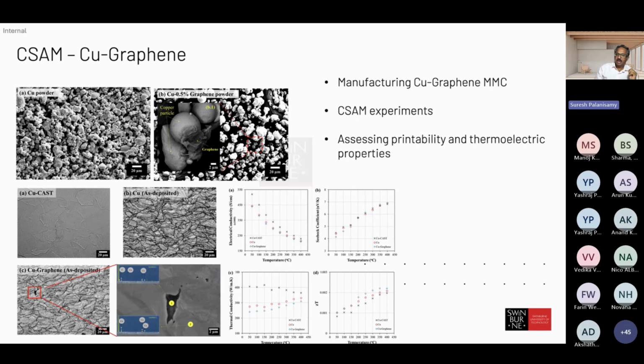So multi-material, interestingly, somebody was asking earlier about metal matrix. Here we call it metal matrix composites. So copper incorporated with graphene particles, just 0.5% of the weight, or 1% itself, is enough for graphene to be mixed with copper particles and deposited. And we can see that it gives better thermal conductivity. The Seebeck coefficient is far better, and it gives far better thermal conductivity when you compare to using graphene copper material, and different conditions, different better properties can be achieved.